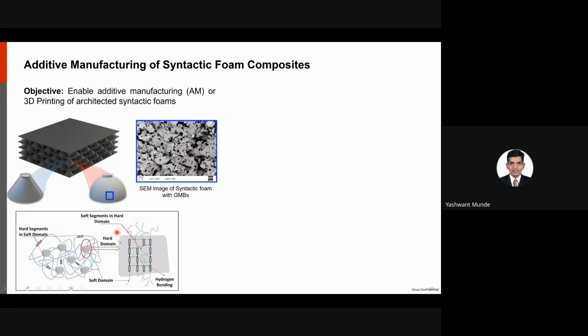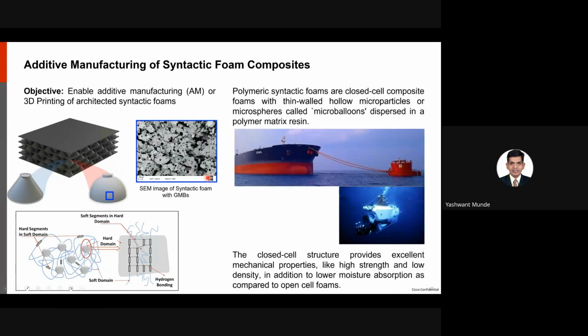Now in our work, as I said earlier, we are not manipulating these aspects. We are fixing the hard domains in our material, but more so tailoring the internal architecture at the micron length scale. So what are polymeric syntactic foams? These are closed cell composite foams with thin wall hollow microparticles or microspheres called microballoons, which are dispersed in a polymer matrix resin. These are used widely in marine applications for buoys, as well as underwater remotely operated vehicles like Alvin, as shown here. Because of this closed cell structure, they provide excellent mechanical properties like high strength and low density, in addition to lower moisture absorption compared to open cell foams.